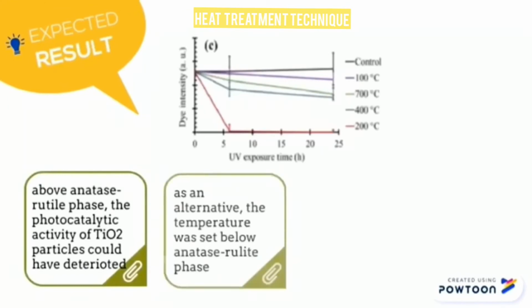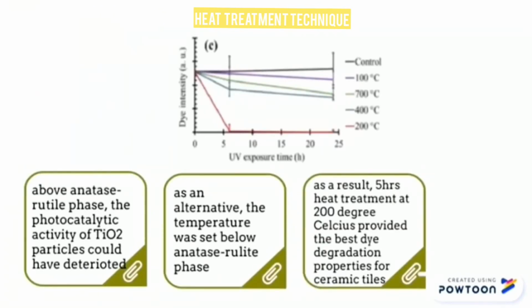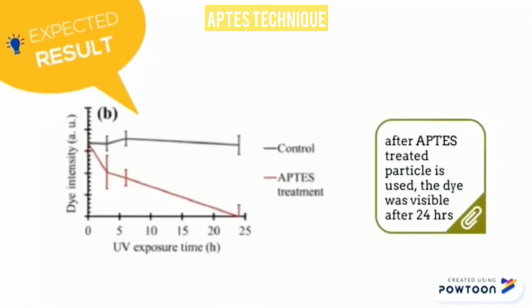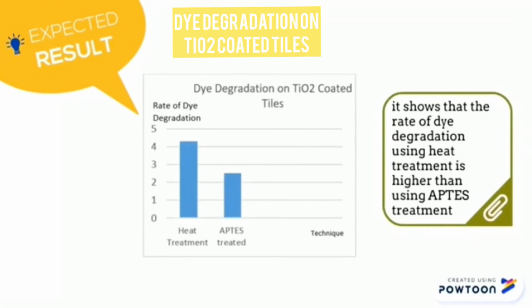So this is the result for the heat treatment technique. If the temperature is above the anatase to rutile phase transition, the photocatalytic activity of titanium dioxide particles could deteriorate. As an alternative, the temperature was set below the anatase to rutile phase transition. As a result, 5 hours of heat treatment at 200 degrees Celsius provided the best dye degradation properties for ceramic tiles. This is the result of the ceramic tiles coated with the APTES treatment method. After APTES treated particles were used, the dye was still visible after 24 hours. To conclude, the rate of dye degradation using heat treatment is higher than using APTES treatment.